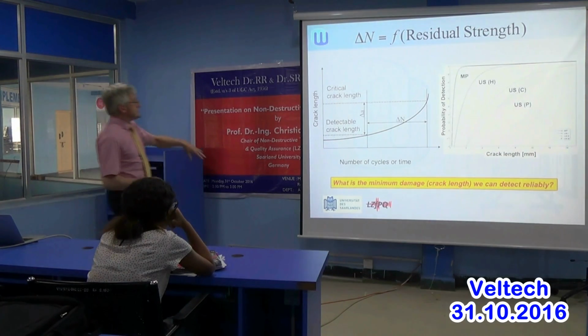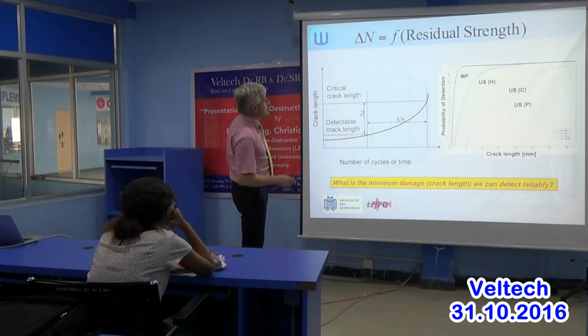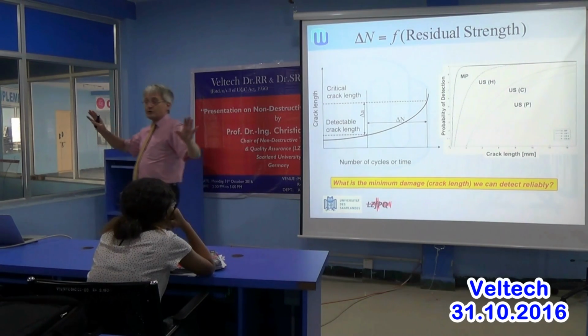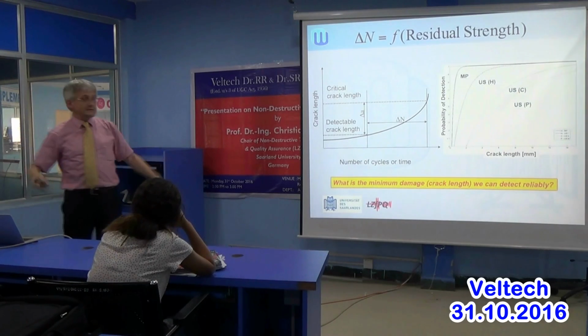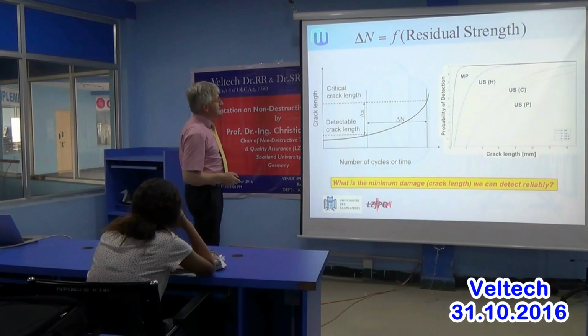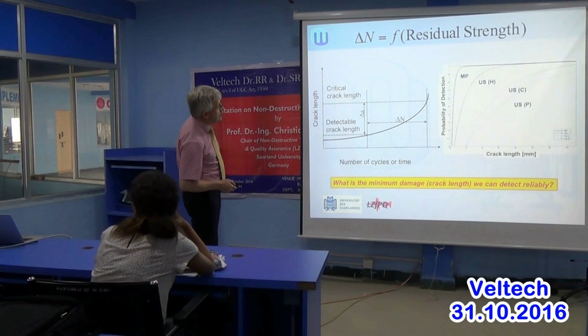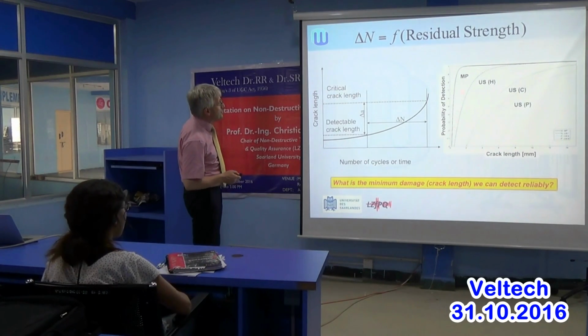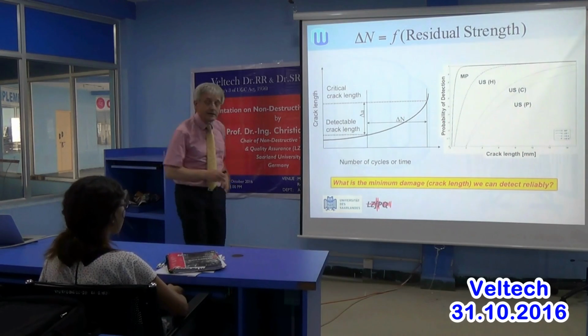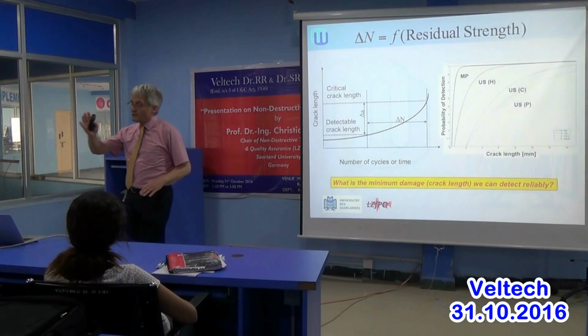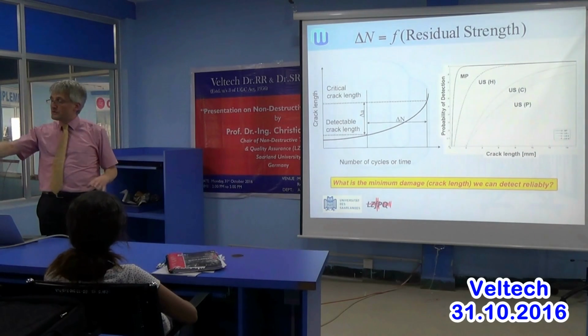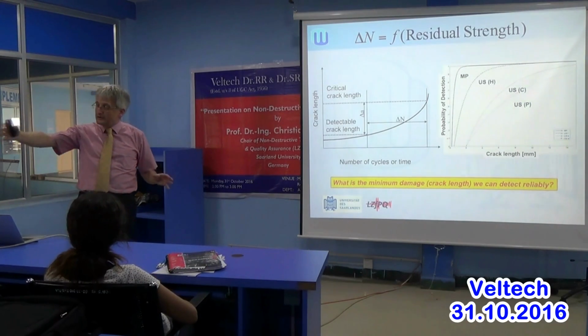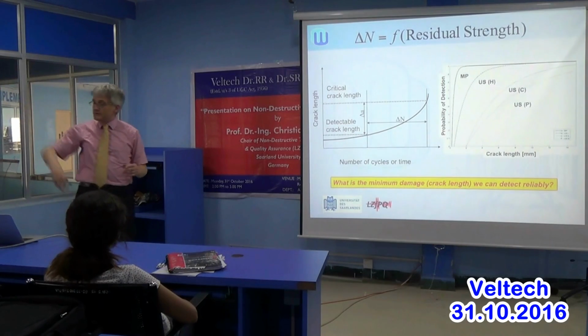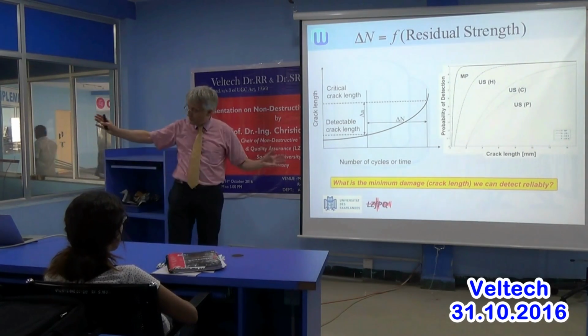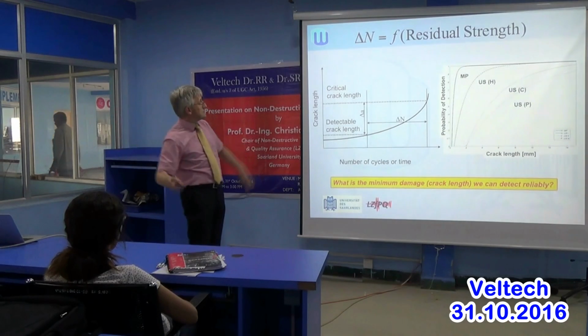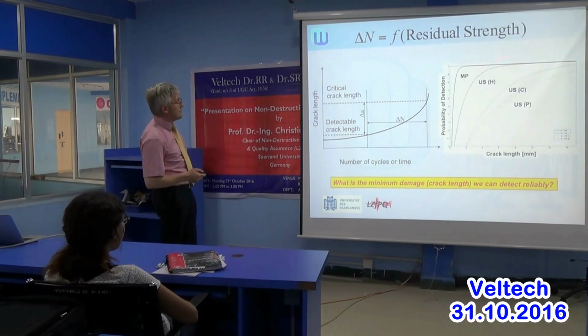Right, then there's a few additional things. That's the same thing we had here. Then there's of course which technique, and we're just going to look now a little into the different techniques which exist. And there are some techniques where you see the crack better and where you see it less. And we call that the probability of detection. So we assess even how good cracks can be seen. If I would give you a different crack length, then you would expect that each of us would have a different probability of detection. There would be cracks you would see 100%, and others you would not see 100%. So this is an information you also need.